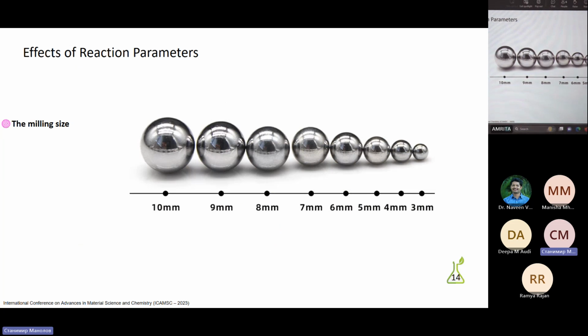The milling ball size directly changes the surface properties of the synthesized materials. The large or high density balls can supply high collision energy and increase the surface activity that causes the forming of thermodynamically stable products. The small balls increase the frictional action that helps to form amorphous and metastable phases, and they are generally selected if more efficient mixing is required.